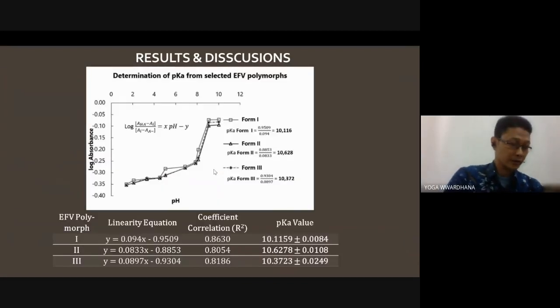We found that the highest pKa is from form 2 at 10.628, then from form 1 at 10.116, and from form 3 at 10.372. This is correlated with the solubility and also the dissolution properties.